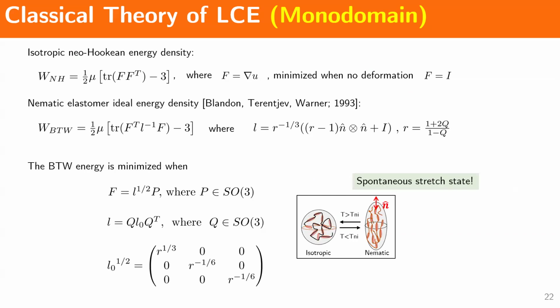And in particular, if we look closely as to what this is, now we have new energy minimizing states that are different from before. Now, the new ground state will be some rotation of this particular base tensor, which is a uniaxial stretch state, right? And if we remember, we've seen this before, this corresponds to the spontaneous stretch state under the phase transition, right? So this is a uniaxial stretch state, and this gives you basically the energy minimizing state where you have this low stress behavior.